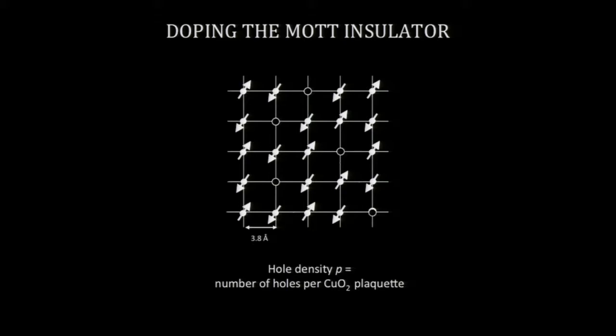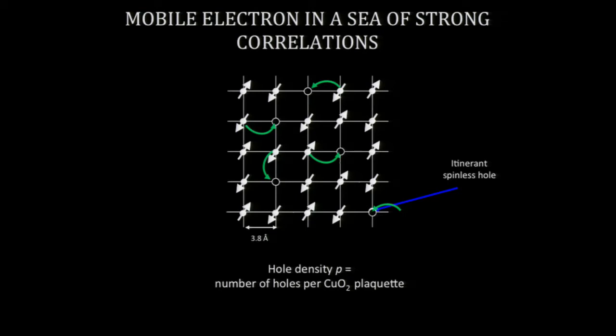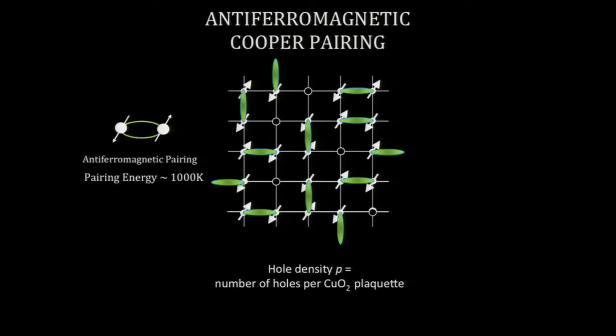But what you could do is put holes into the system. You can remove an electron. And now the electrons can move. So now you have some mobility in the system. And you also have the fact that you have this antiferromagnetism. And this very much looks like what you would have for pairing, taking two fermions and pairing them to make a Cooper pair. So you have what looks to be like Cooper pairing, and the exchange interaction is actually quite high. The scale is about 1,000 Kelvin. And now they're mobile. So this seems to be a nice platform in which you can have a 1,000 Kelvin superconductor.